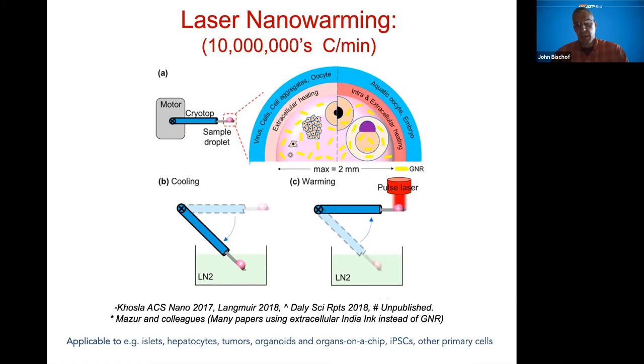And we actually adopted that for this purpose. And we micro-injected the gold nanoparticles directly into the embryo. We demonstrated that there was a sufficiently uniform distribution of the gold, and then we would vitrify first on the left, and then with an automated system, we would bring this under a pulse laser. This is a millisecond pulse laser, and we could bring back zebrafish.